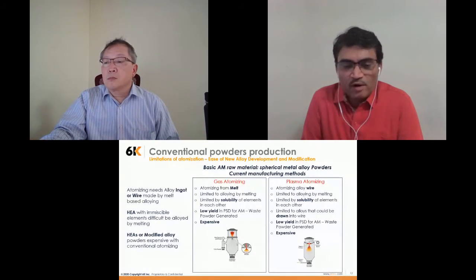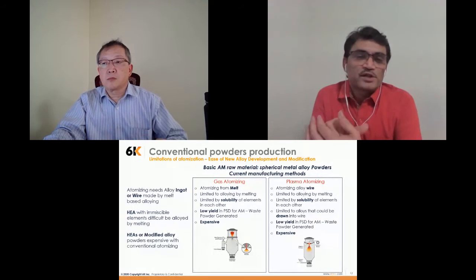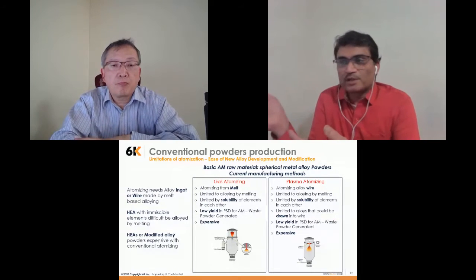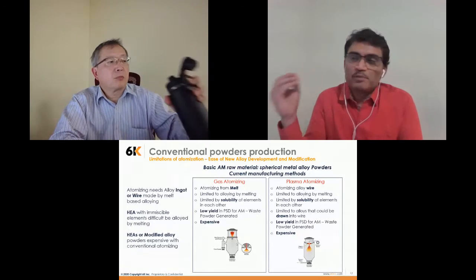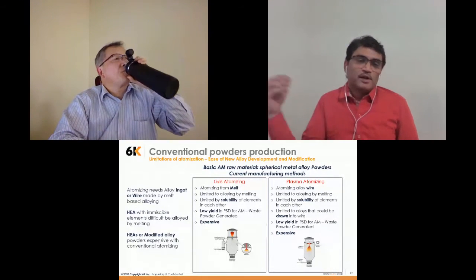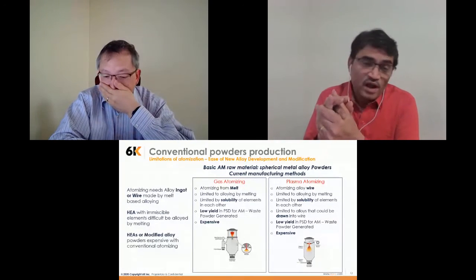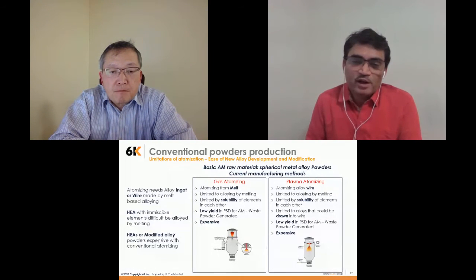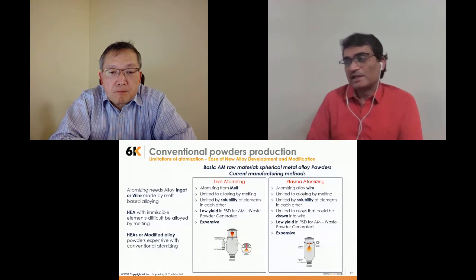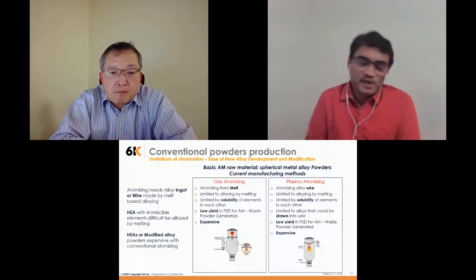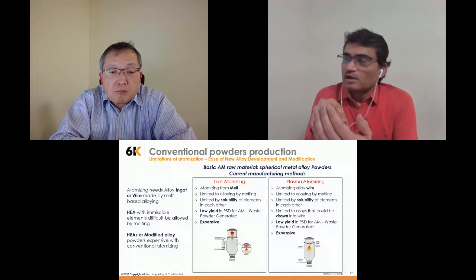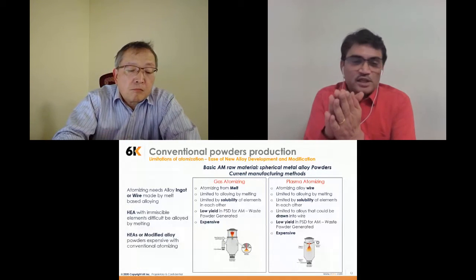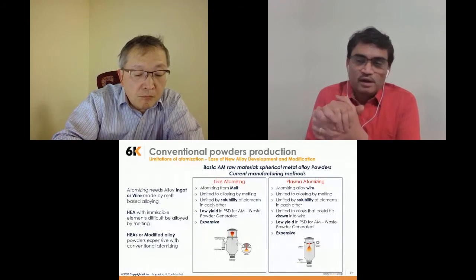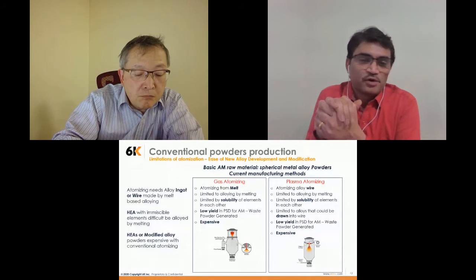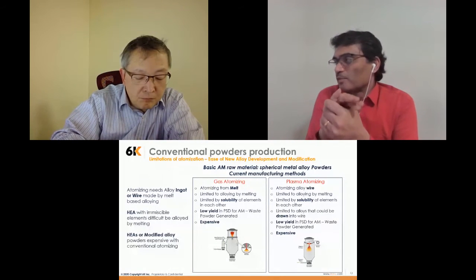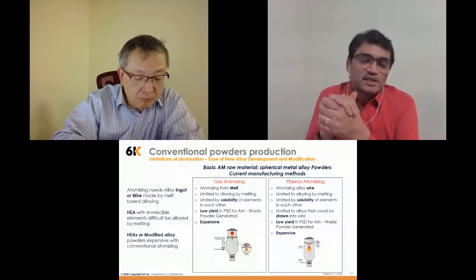And basically for powder production, currently powders are produced by either gas atomizing or plasma atomizing. Both are melt-based technologies. The input for gas atomizing is ingot, which is produced by melting, and the input for plasma atomizing is wire, which is also made by melting. So for alloys which are difficult or expensive to manufacture by melting, we cannot use gas atomizing or plasma atomizing. Otherwise, it will be more expensive. The other limitation of gas atomizing or plasma atomizing is the yield. Especially for additive manufacturing, a very popular particle size distribution is 15 to 45 microns. And in either gas atomizing or plasma atomizing, the yield is maximum 30%. So 70% is oversized or waste. It is recycled.